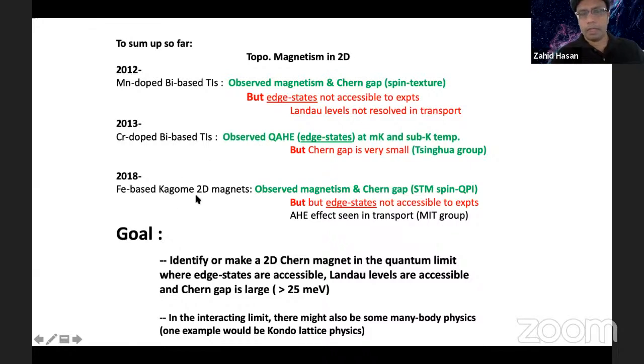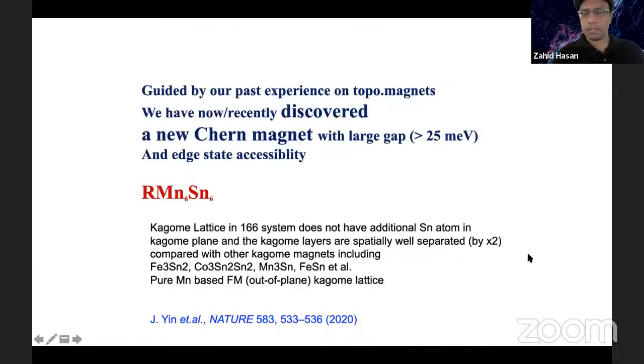Then it was shown that in Kagome magnets, you can see both exchange magnetism and a Chern gap, and clearly show that without doing transport, you can probe the Chern gap, which is important because that allows you to engineer the material to a desired goal. So what is that goal? The goal is to find a topological magnet in the quantum limit whose edge states are accessible, Landau levels accessible, and the Chern gap is large, possibly operating at room temperature, which should be more than 25 milli-electron volts or so. And also there is some sort of interaction, so there's more fun in the system and you can probe some many-body physics.